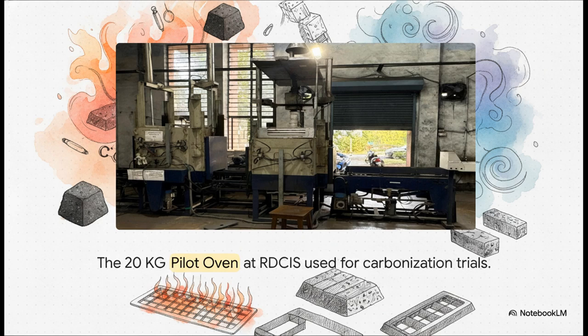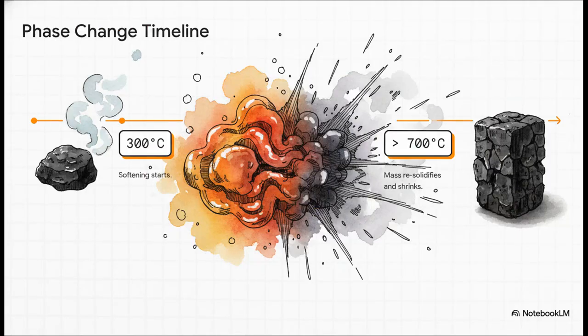And because there's zero oxygen, the coal doesn't burn. Instead, it carbonizes. Tracking the thermal journey this rock goes on is honestly fascinating. Up to 250 degrees, it's just drying out. But at 300, it softens, heading right into the critical plastic stage between 350 and 550 degrees. In this very specific window, the coal literally melts, swells, and fuses together.